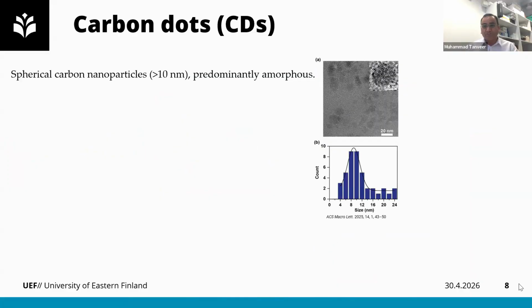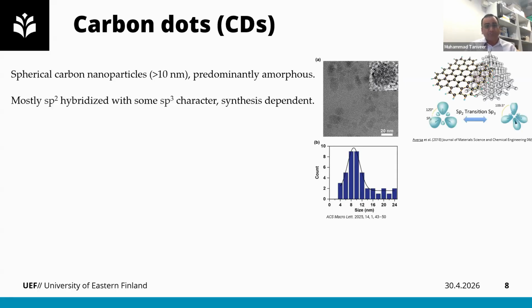nanostructure? These are very fine particles around 10 nanometers in size. Predominantly, they are amorphous, and they also have some crystalline cores that can induce particular features in these nanostructures for photoluminescence and optical properties. Also, they are mostly sp2 hybridized with some sp3 fractions. It depends upon the synthesis route, like whether you are using a bottom-up or top-down approach, so you can tune the requirement of sp2 or sp3 structure in your carbon dots according to your application.